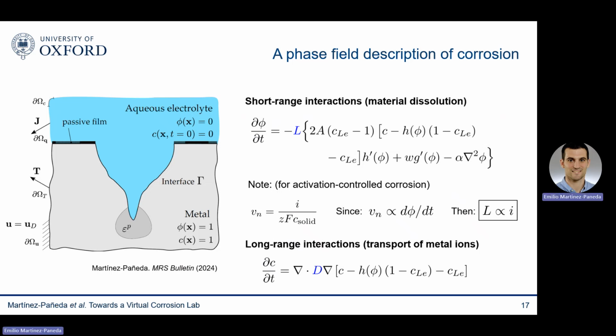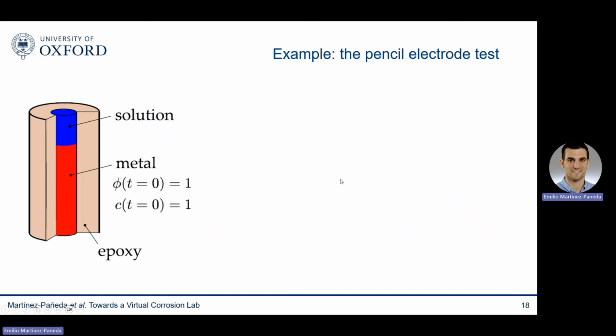The key thing that I want to emphasize is that the upper equation is governed by this mobility parameter L, and the bottom equation is governed by this diffusion coefficient D, and both have a clear physical meaning. The diffusion coefficient is obvious, and as for the mobility coefficient, you can easily demonstrate that it's proportional to the corrosion current density. So it's straightforward to quantify this value of L from a simple uniform corrosion experiment. So let me show you how this works with the simplest example, the pencil electrode test, which is effectively 1D corrosion, as you have uniform corrosion of this metallic bar.